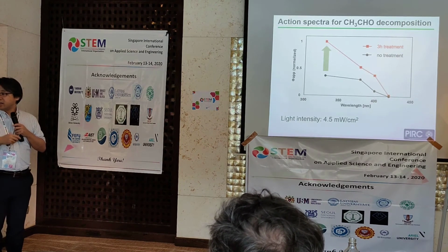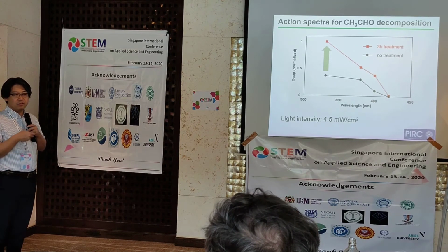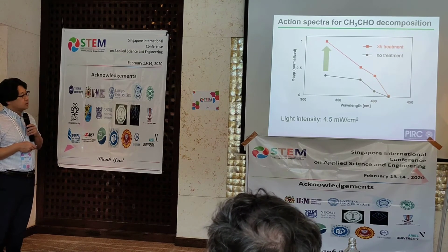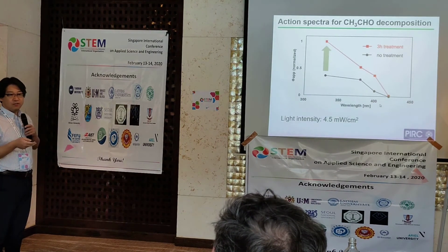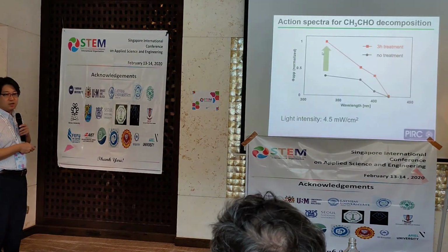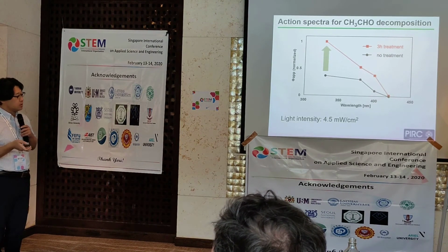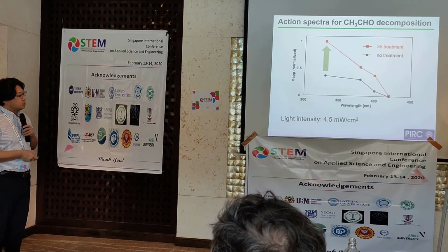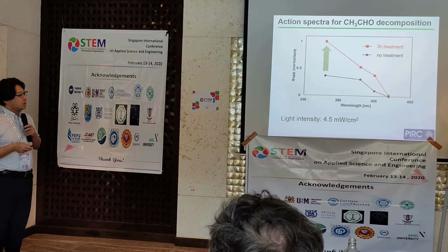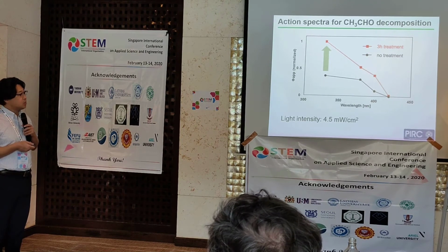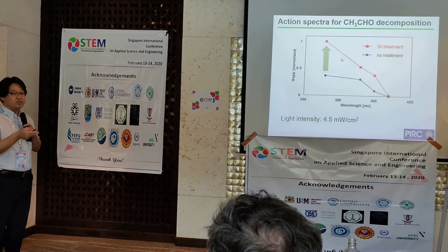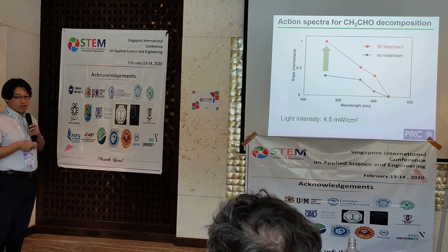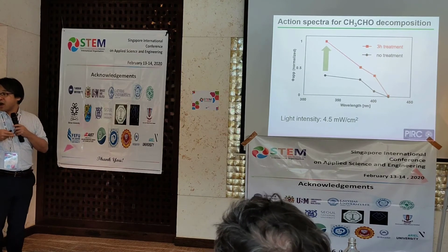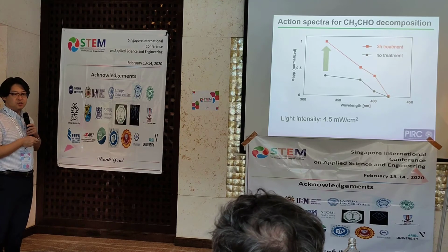So we studied why our sample shows this activity using a fluorescent lamp. This is the action spectrum. The x-axis is the irradiated light wavelength, and the y-axis is the quantum efficiency from acetaldehyde to carbon dioxide. This black line is pristine TiO2 and the red line is after plasma treatment. Please see around here, the visible region. Both samples show no activity at around 420 nanometer wavelengths. But in our sample, the activity is more than 2 times higher than pristine TiO2. That means our sample doesn't show visible activity, it only enhances the UV region quantum efficiency.